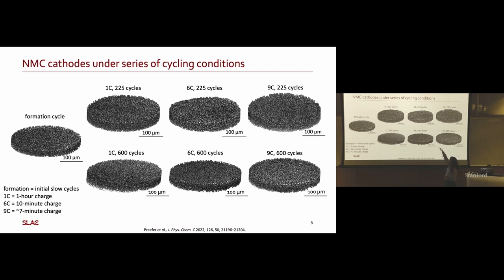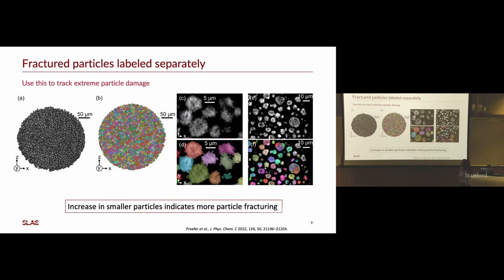And we looked at it after 225 cycles and after 600 cycles. So really long-term cycling. And you can't tell much from these. Each of those circles that you're seeing are individual cathode particles, and you're looking at about a millimeter distance, a radial distance, a diameter. But now that we have this data, we can actually take it and do something with it. And so we're able to label every single particle in the 3D map.